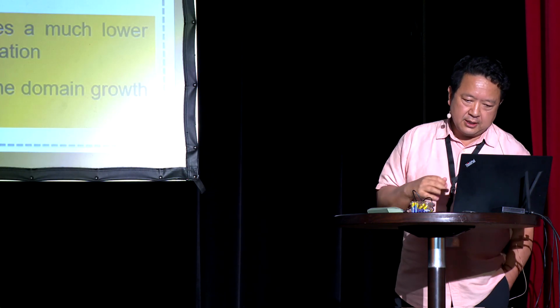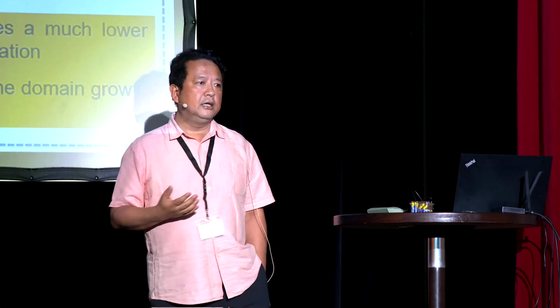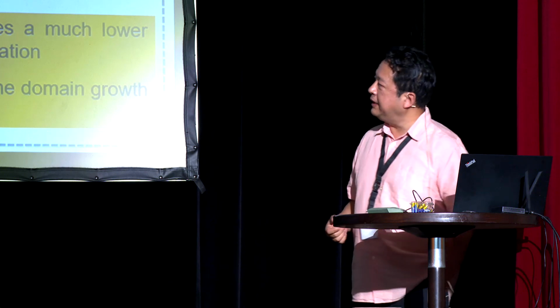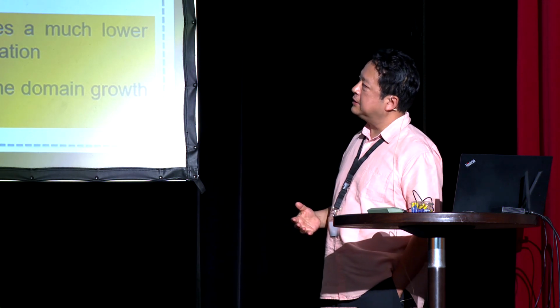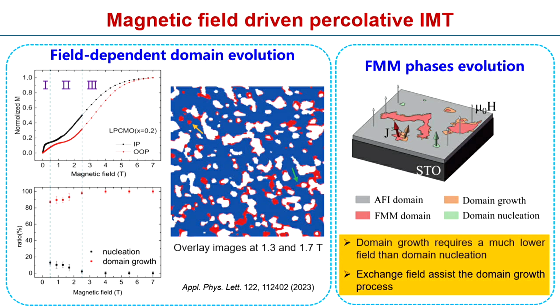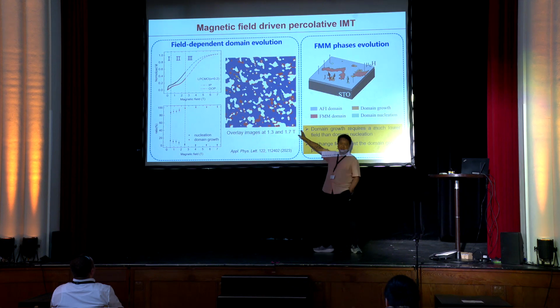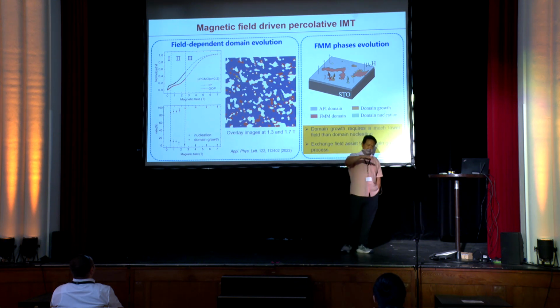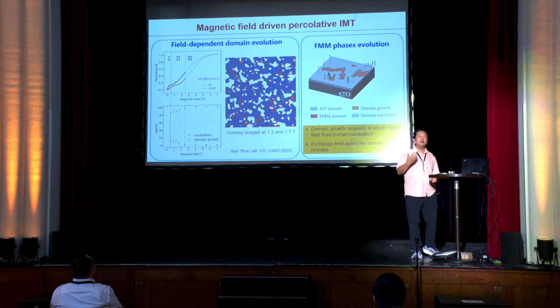looking at these images. Now, how are we going to reduce the required field? To make this high magnetic resistance, right? So the idea is that we study this evolution of these electronic phases as a function of magnetic field. We find that the field required for the domain growth is much less than the domain nucleation. I'm not going to show you the details, but we compared all these series of images, and then finally we can reach the conclusion that the domain growth requires much less field than the domain nucleation. So now the idea is becoming, how are we going to introduce the nucleations without external field?